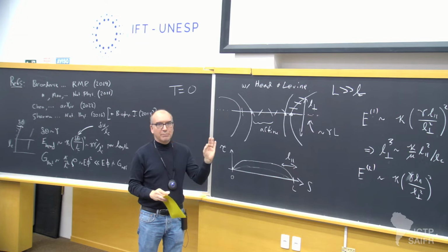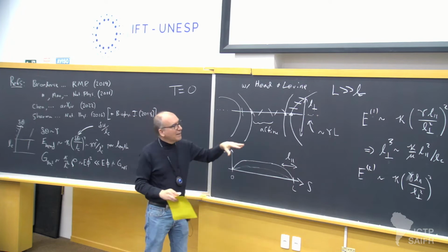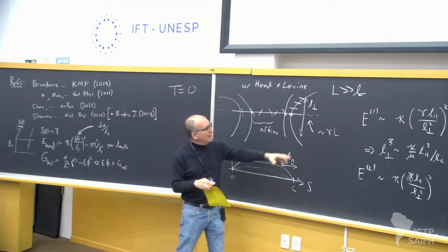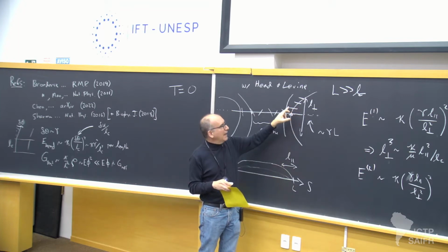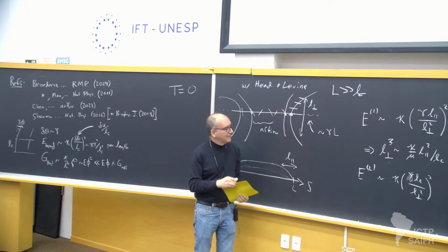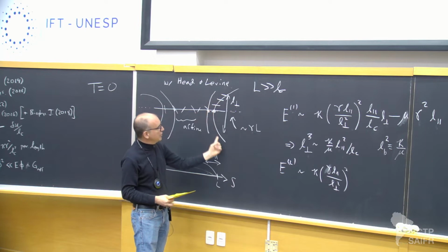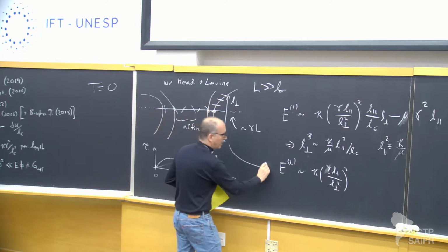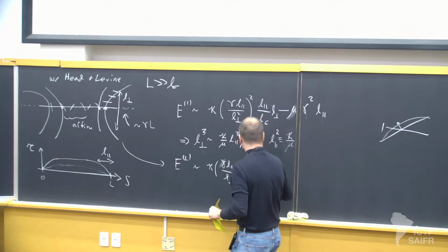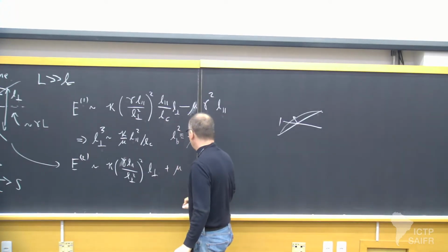But the important thing about 2 dimensions, and so I'm going to go through this argument first in 2 dimensions, and then just tell you what happens in 3D in interest of time. But in 2 dimensions, these filaments are highly constrained. That means that for these bends to occur here, I've got to introduce some stretching and compression of additional fibers that they're cross-linked to. Okay, so what I'm going to do now is just calculate the bending energy of one of these. So take this fiber and calculate its bending energy. And now I multiply by L perp, because that's how much I have.